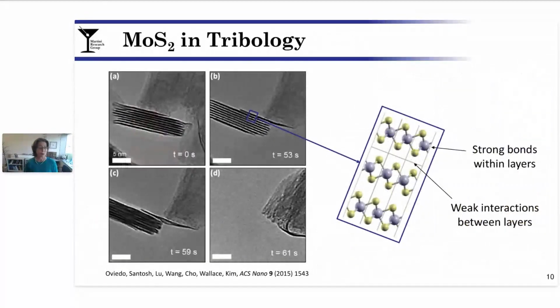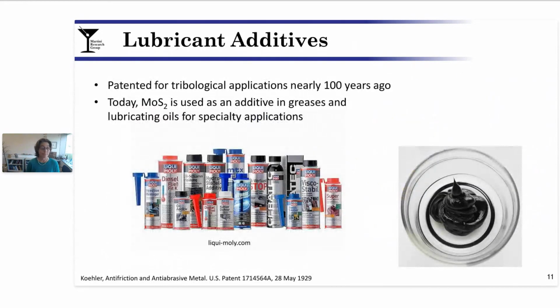However, from a tribological perspective, the most important aspect of molybdenum disulfide, or MoS2, is this layered structure, where we have very strong bonds within layers and very weak bonds between them. What this enables is the layers to slide very easily relative to one another, such that the material has low shear strength and imparts for us low friction and wear and good tribological properties. MoS2 in lubrication is nothing new. In fact, the patent for MoS2 as a lubricant additive is almost 100 years old now. So it's been around for a while. And in fact, one can purchase MoS2 additized lubricating oils and greases for specialty products online even today.